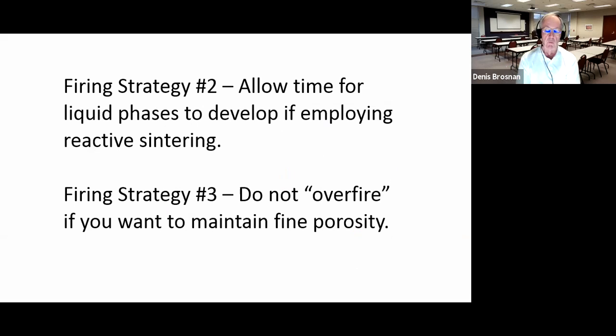So what we talked about in these alumina porcelains, 90 to 95% alumina compositions, is that you want to allow time for liquid phases to develop, which might say you want to ramp in the firing schedule. You want to allow the liquid phases to develop, and once you've given them time to develop, you can ramp up to higher temperatures to enhance the sintering process. Remember that primary mullite is the main thing that you're looking for, because the liquid phase percentage is so small, secondary mullite really doesn't come into play. So that's for reactive sintering. Firing strategy number 3, don't overfire the product if you want to maintain fine porosity for the reasons that I said.